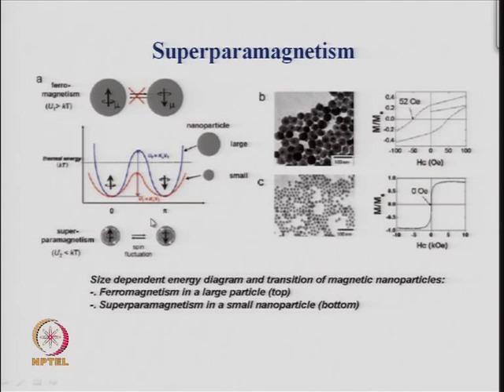So, this way, and when will this happen? This will happen whenever the energy required to flip the two vectors is lower than the thermal energy. So, that is the key point, that the energy to change from one vectorial direction to another vectorial direction is much smaller than the available thermal energy, then you will see this kind of superparamagnetism, which is highly prevalent in magnetic materials and is a function of the size of the particle.